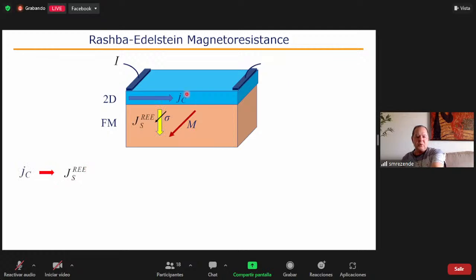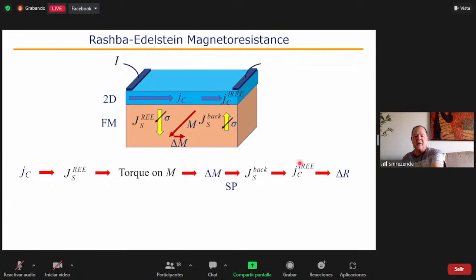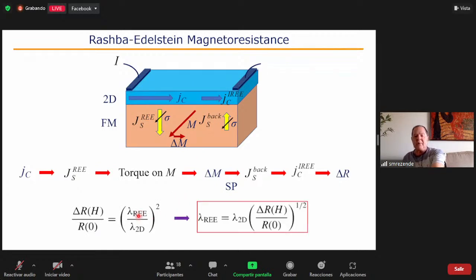Well, the charge current will produce a spin current by the Rashba-Edelstein effect. This spin current flows into the magnetic material. It produces a torque in the magnetic material. The torque will produce a counter spin current. The reflected spin current is converted into another charge current, and this charge current then adds to the previous one. The result is a change in the resistance. This is also magnetoresistance. And one can show that the change in resistance is proportional to the Rashba-Edelstein parameter.